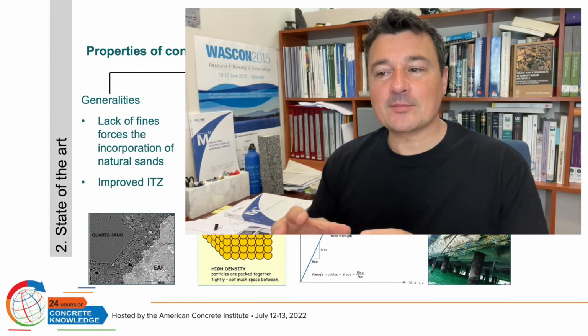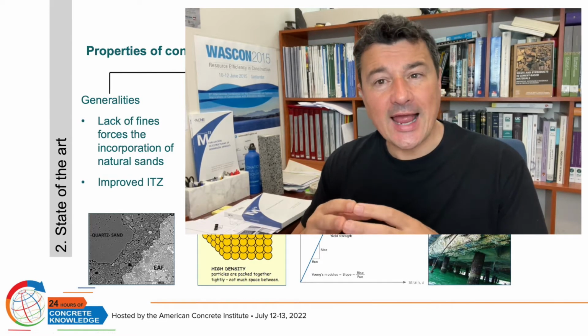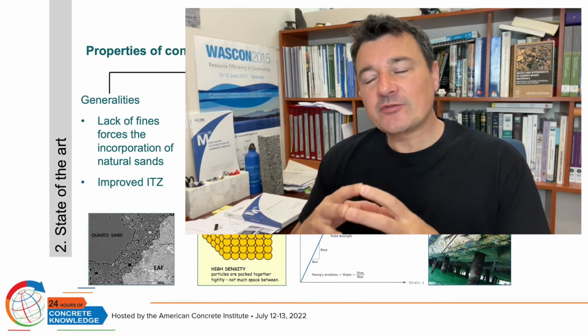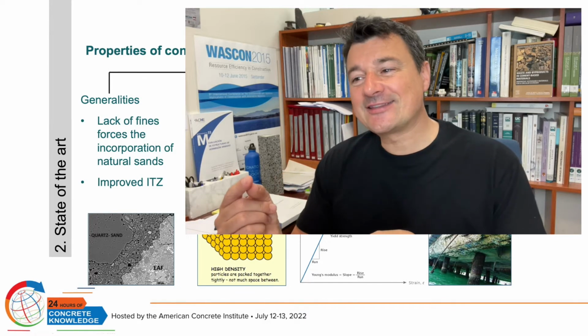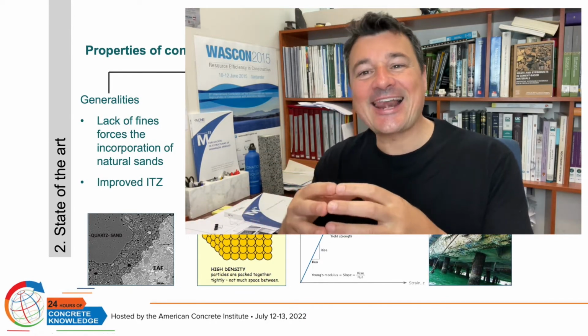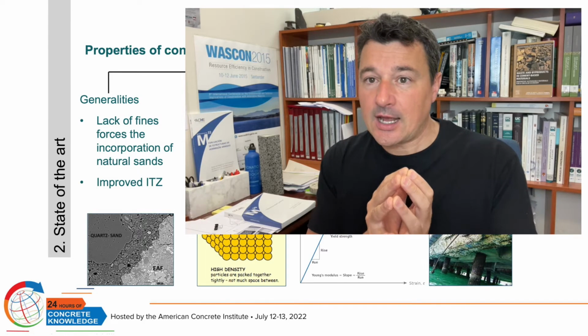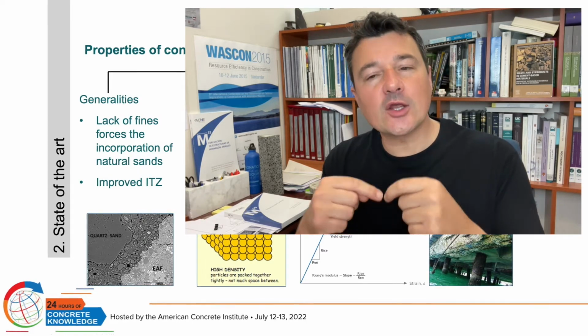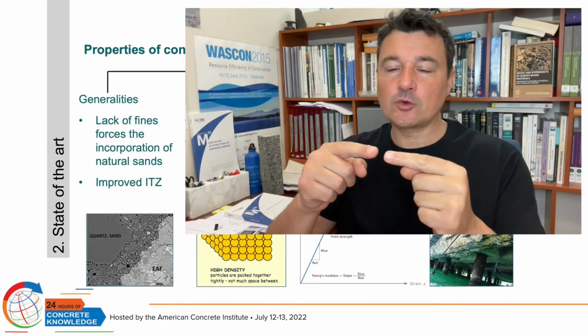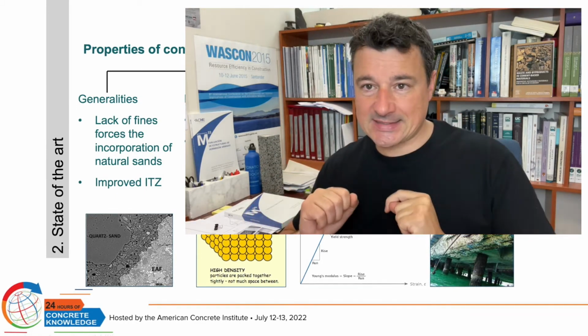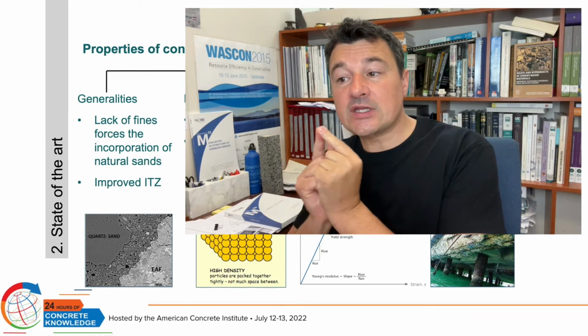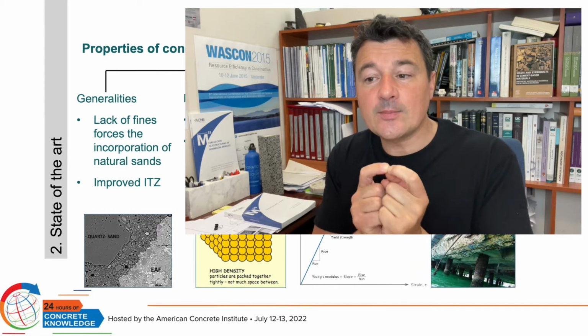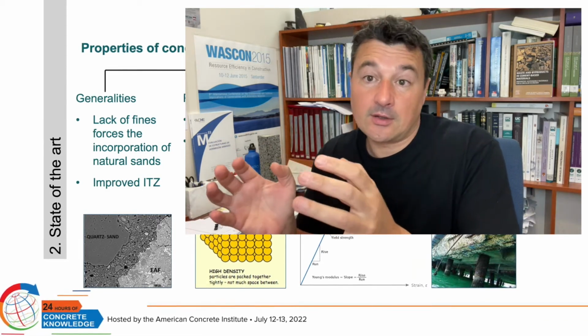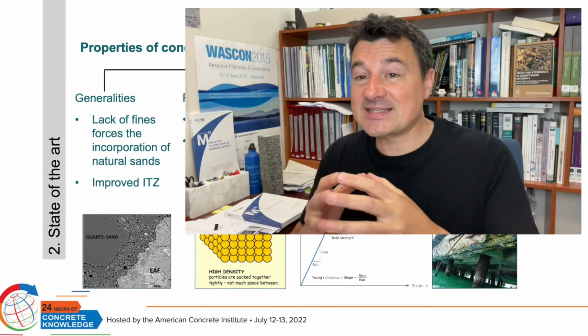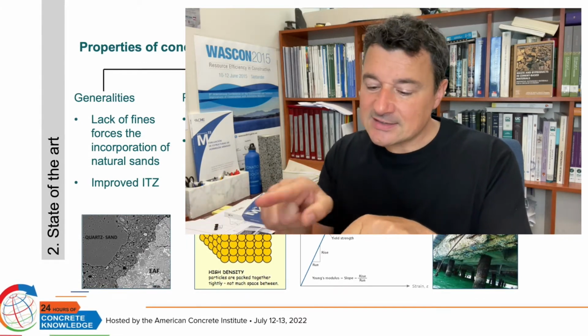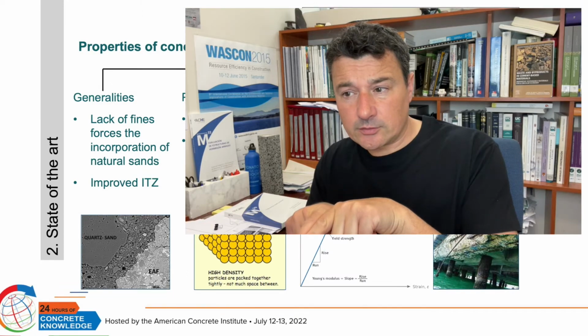What are the main properties of the siderurgical aggregate concrete? We have to take into account, firstly, that the siderurgical aggregate presents a lack of fineness, and it supposes that we have to incorporate extra sand to close the aggregate skeleton. But also the use of siderurgical aggregates improve the ITZ of the material, in this case, especially the bond between the cement paste and the aggregate.